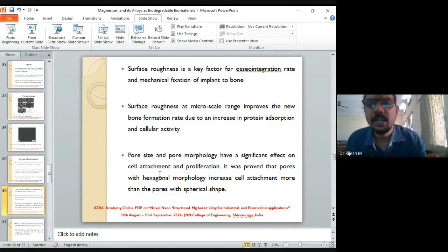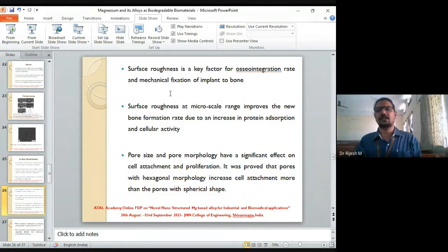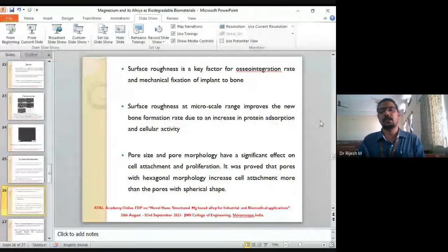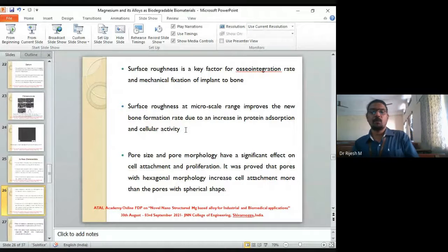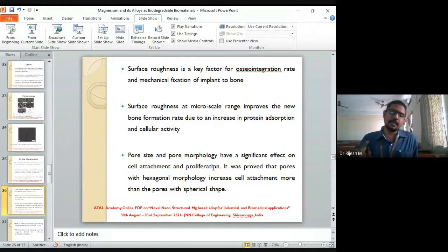So if your bioimplant has this small surface roughness in the microscale range, due to those pores, you can increase the protein adsorption and cellular activity, thus healing the bones. Pore size and pore morphology have a significant effect on cell attachment and proliferation. It was proved that pores with hexagonal morphology increase cell attachment more than pores with spherical shape. Again, that is more important.